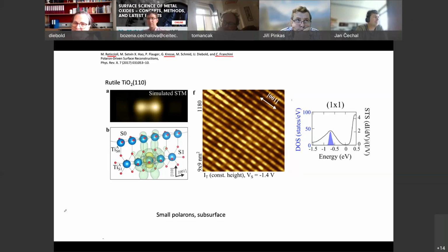But the hopping mechanism is, they hop with a frequency of about 10 to the 12 per second from one to the next, with the frequency of lattice phonons. The tunneling between the tip and the sample goes really fast, faster than 10 to the minus 15 seconds. So while we tunnel into the tip, the next electron localizes there and can tunnel out. Next, one electron comes there, localizes, and can then tunnel out. Next one comes and tunnels out. Okay.